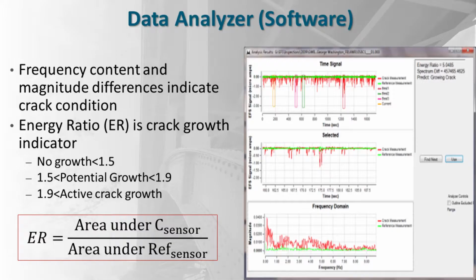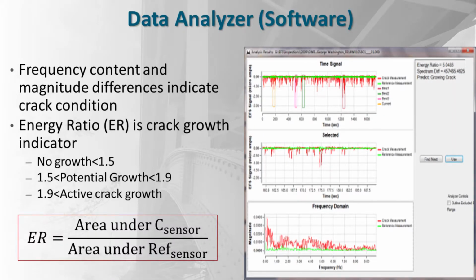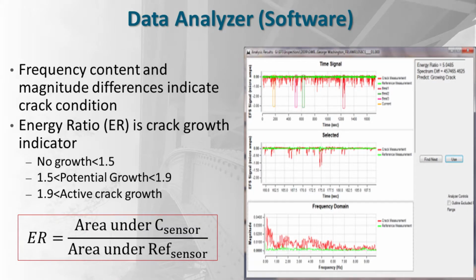And when we compare those 2 signals, we have what we call the energy ratio of a crack. The energy ratio of a crack is the area under the curve of the sensor that is on top of the crack or near the crack, over the area under the curve from the reference sensor. We have thresholds for that. If it is from 1 to 1.5 ratio, the crack is not actually growing, it's just experiencing elastic deformation. If that ratio is from 1.5 to 1.9, it's showing microplasticity, a precursor to crack propagation, and above 1.9, the crack is actively propagating.